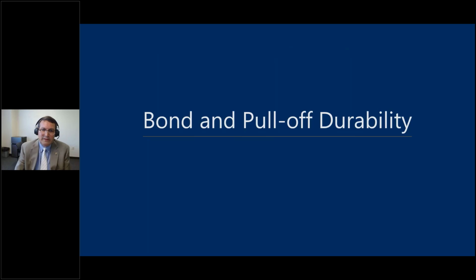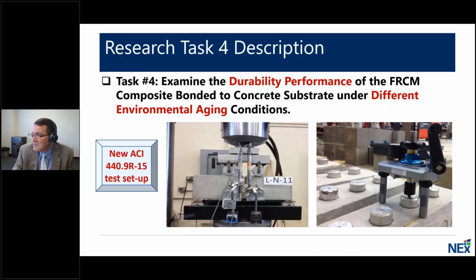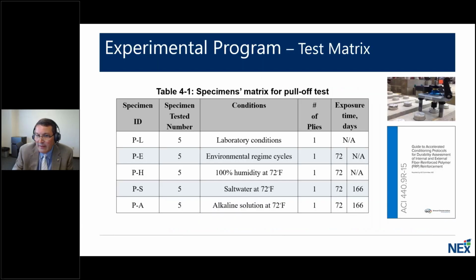Now we'll move quickly into task 4, which is looking at the bond performance of these systems. In task 4, we examined the durability performance of FRCM under varied environmental aging conditions. These are durability and condition exposure tests using the ACI 440.9R-15 document, basically using the beam bending test on the left and the direct tension pull-off test on the right.